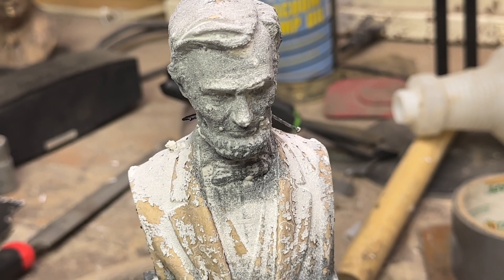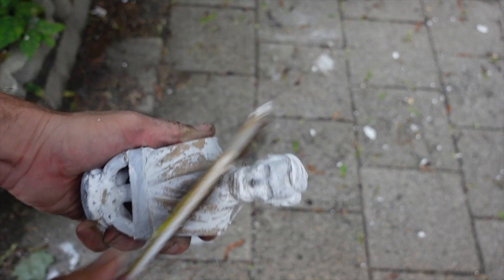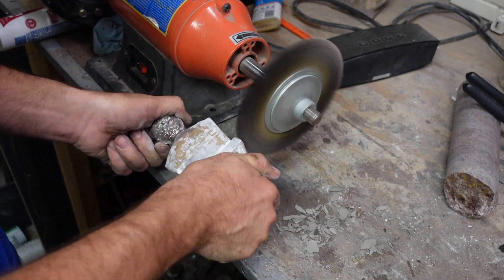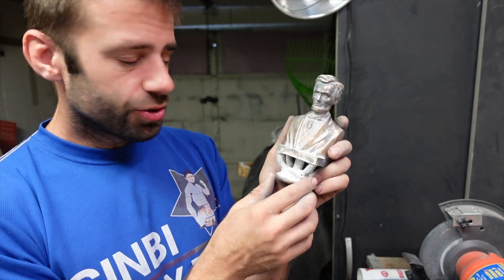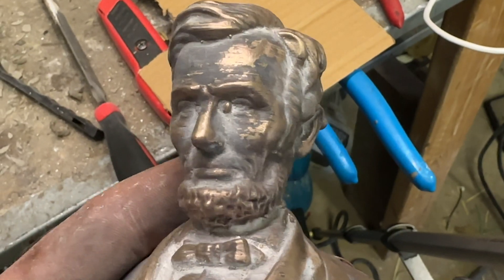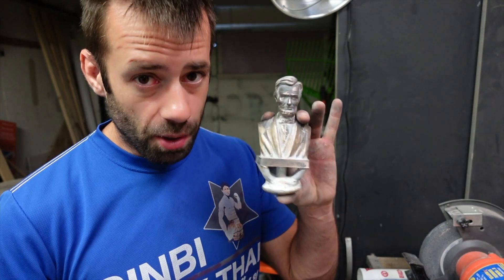It's looking pretty good, but just like I feared, there are a few bubbles. I'll get it cleaned up a little better and we'll take a closer look. The surface finish turned out great — doesn't have that pockmark, there's no sign of ash. There are some very unfortunate bubbles, including one right in the eye. Bubbles in the eyes always suck, but that has nothing to do with the PLA. There are still a few layer lines visible, but overall really good. Let's go try the Polycast now.